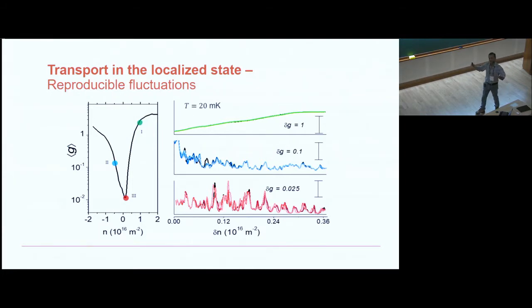These are essentially realizations of different disorder profiles, okay? So each and every point here is an ensemble, which is changed as I change the electron density. There are 4 sweeps, and they all fall on top of each other. These are not noise. These are actually electrons facing certain resistances, the different ensembles. Okay, so what we do is calculate the mean of the conductance and the variance of the conductance and look at the self-averaging property. I'm going to skip a little bit.